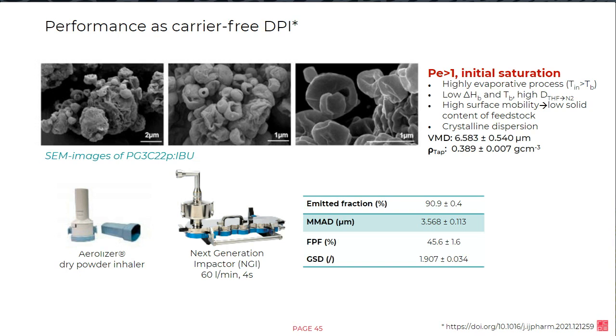The emitted fraction of the product is quite high, 90%, meaning that only 10% of the product is staying in the inhaler, which is quite a nice number compared to carrier-based formulations. This is actually associated to surface corrugation in the particles and the lipidic composition on the surface, and this was provided by a high surface mobility during drying because of the Peclet number above 1 and also a low solid content of the feedstock, which was only 1.5%.